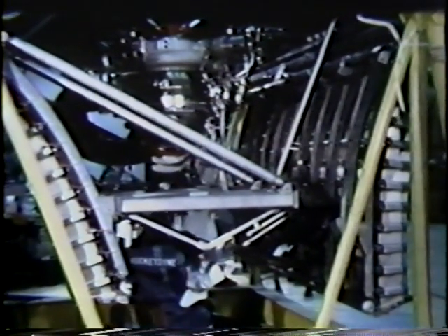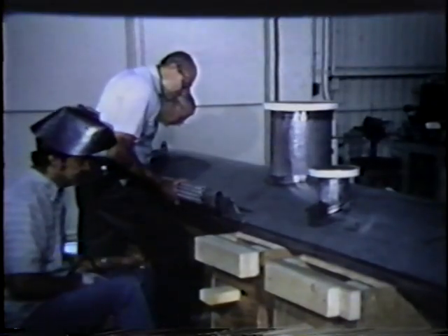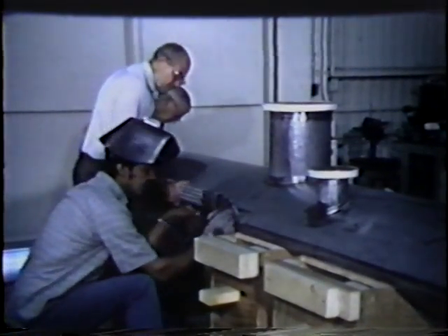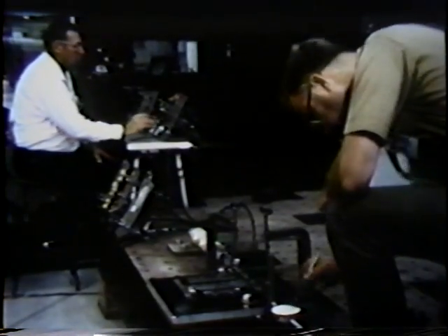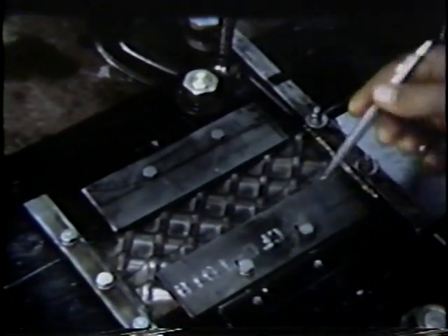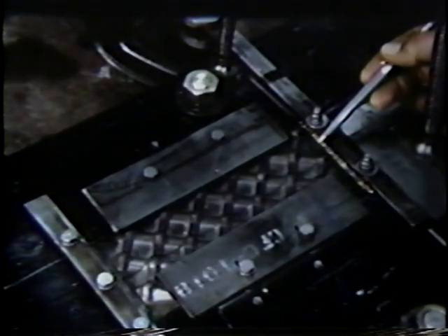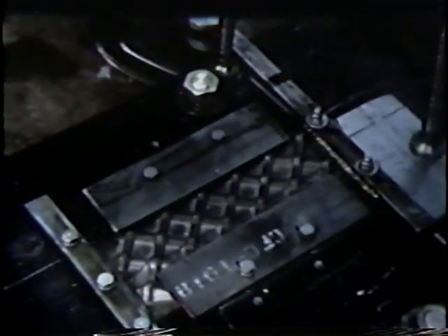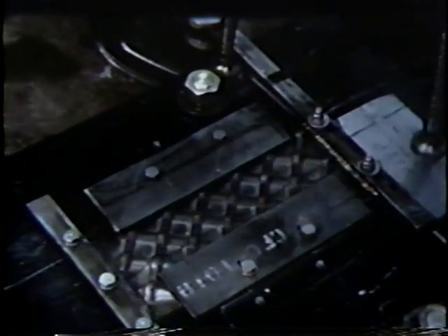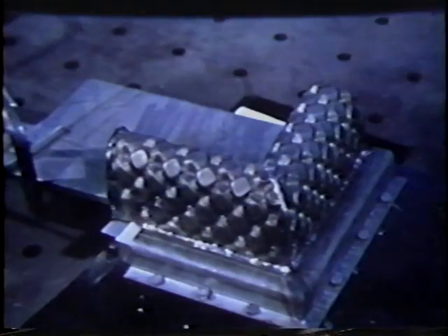Installation of the second side was accomplished with the manifold assembly removed to provide access. Before final installation of the center body, it was fitted with a hot gas seal around the perimeter. The seal is designed to prevent primary and secondary gases from escaping upward into the central assembly. Development of a satisfactory seal was the result of a research and development effort to find a configuration that could withstand the anticipated thermal stresses without cracking, yet provide the necessary flexibility to absorb movement. Structural tests showed a waffle-type pattern to be most satisfactory, and later tests with sections of corners, the most critical area, sustained this finding.